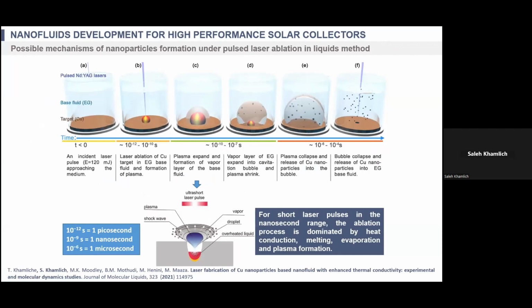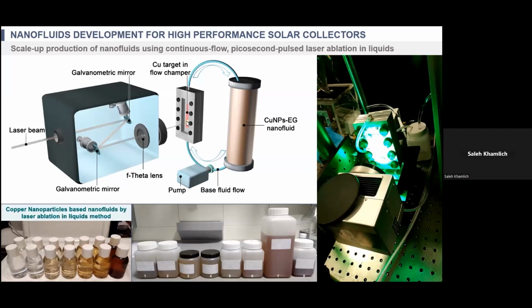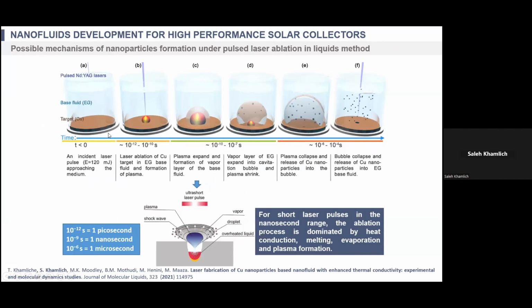The laser, as you can see with me in the previous slide, interacts with the target. So the laser is coming. In our case, we use a copper target. Once the laser interacts with the target, it creates plasma because this laser is highly energetic. It causes the surface of the metal to melt, to create a plasma and to be evaporated also. It melts the surface, and because these pulses are very fast, the melted metal, with the other pulse, is made to evaporate and to create plasma, a state of matter where there are only ions and atoms.